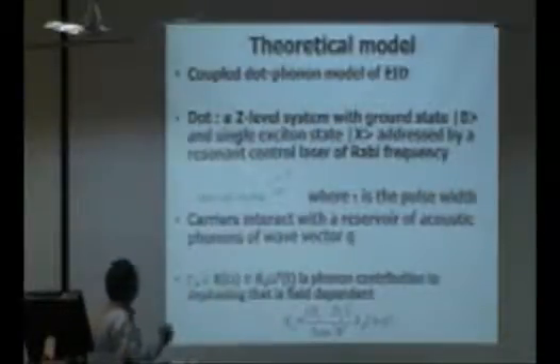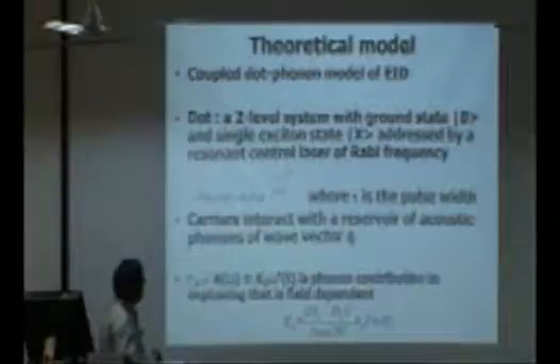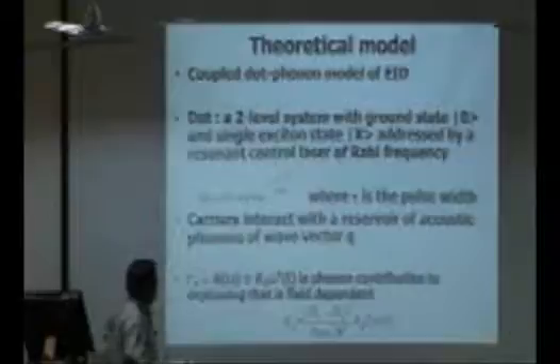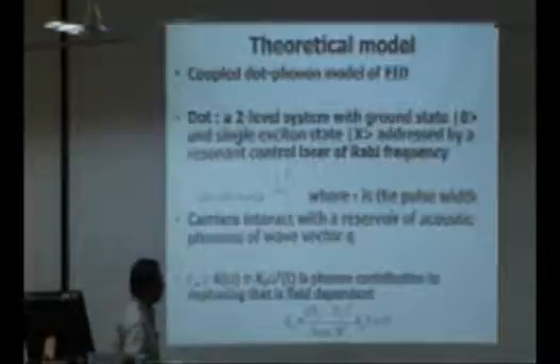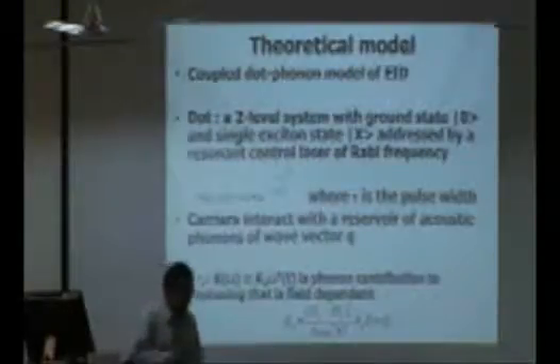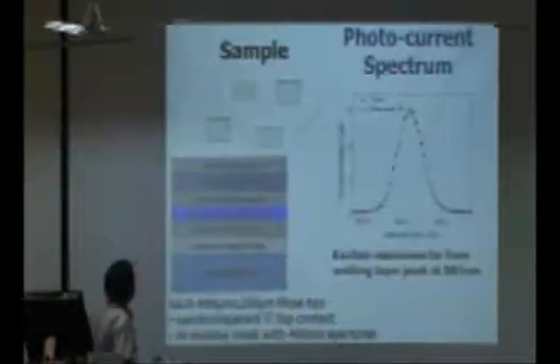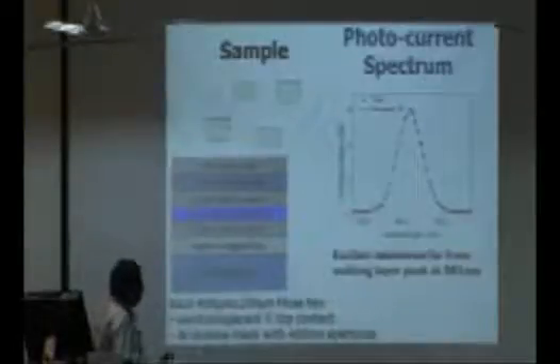The model is straightforward: a coupled dot phonon model of excitation-induced dephasing. The basic final result is that the dephasing rate gamma is proportional to K2 times omega squared, where omega is the Rabi frequency. This K2 is directly proportional to the temperature, with some coefficient A, which depends on the bulk material properties and not on the dot properties. To show this, we picked a sample with low density quantum dots, and we chose the dots such that the dot resonance is far away from the wetting layer peak.